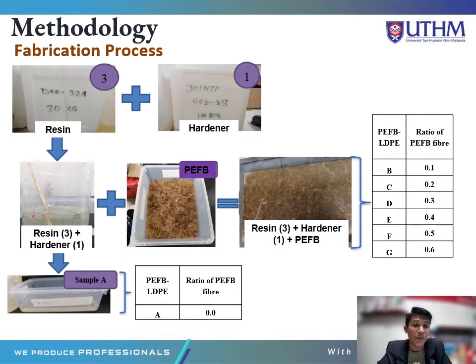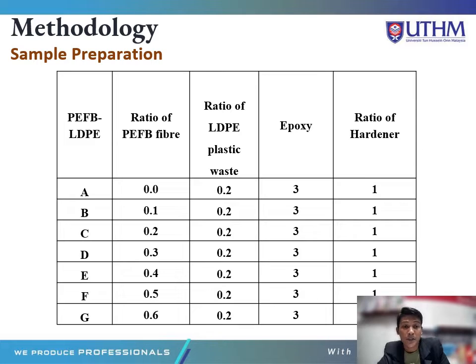This is my fabrication process illustration, which is 3 portions of resin plus 1 portion of hardener, mixed. All the 3 plus 1 resin and hardener will make sample A, while for samples B to G, it should be 3 portions of resin and 1 portion of hardener mixed with PEFB, at a different ratio for each sample, producing samples B to G with different fiber ratios. This is my sample preparation tabulation data of the different samples and different ratios of PEFB.